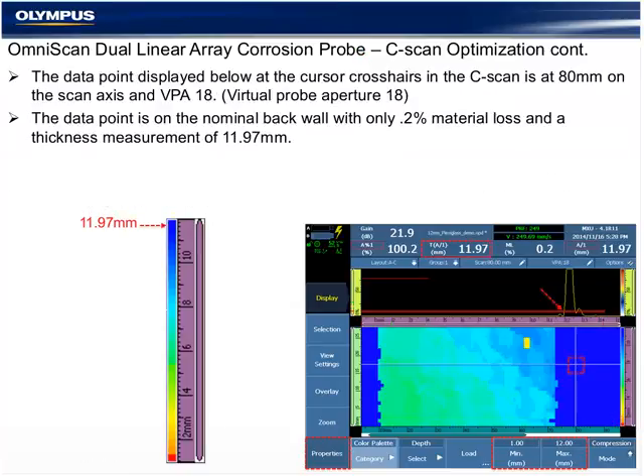When I place the data cursor over an area here with no corrosion, I can see the 11.97 millimeter reading, which was taken at the leading edge of gate A here. It's a 0.2% material loss, and we can see the color associated with it is a dark blue.